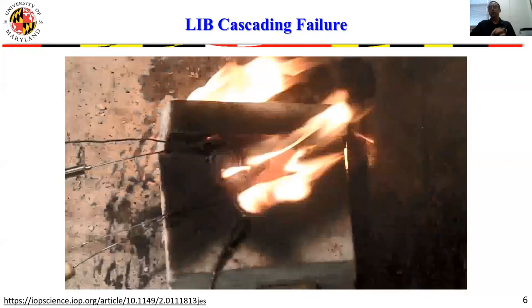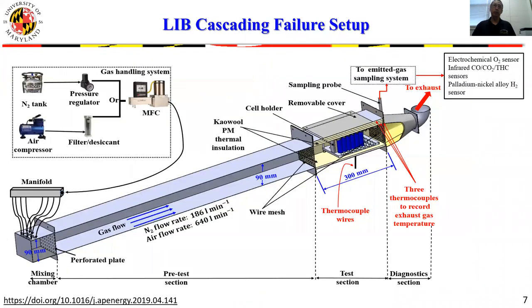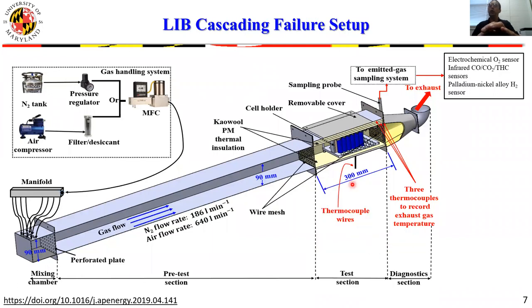So to better understand the dynamics of this failure, we designed this experimental setup shown in this picture. All right, let me go back to my pointer. At the heart of this setup is this test section right here. This test section contains a simulated battery module that we'd like to study. We have an ability here to feed a very well-defined flow of gases of known temperature and composition into this test section. And we have an ability to measure both the composition and temperature of the gases that evolve at the back end as a function of time. And that gives us an ability to understand a lot of things that happen inside the cell, including various forms of heat generation, and also generation of species can be quantified as well.